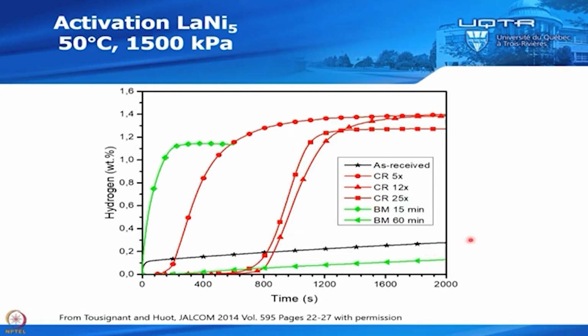So this is the first hydrogenation, the activation at 50 degree and 15 bar. So this is the as received. So you see the as received. It's very difficult. It takes forever to activate. And if you ball mill 15 minutes, you see that it's very fast.